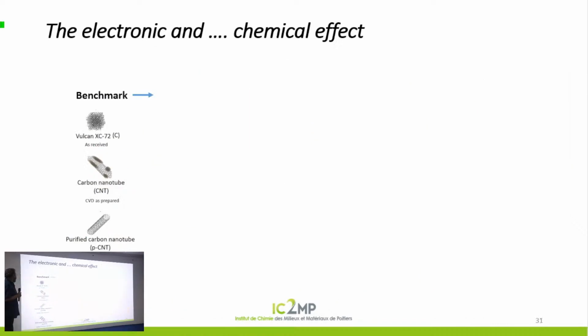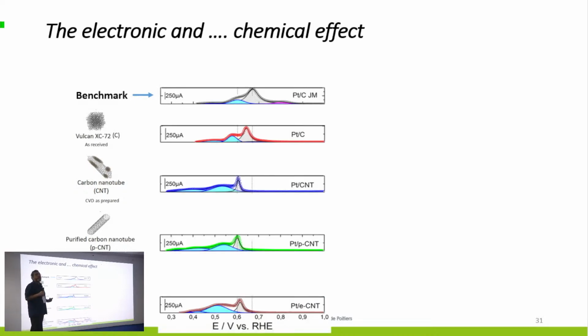Because now what we did is taking into account this support, we did the CO stripping. I don't know if you know what CO stripping is. You polarize the material, you adsorb CO, and this CO adsorbs in a monolayer. Then you scan the potential, and you will observe that the adsorbed CO will be oxidized to CO2. CO is a very interesting molecular probe because it really probes the electronic property of the material. That is a very interesting tool. It's not very expensive at all. And that's indeed what you observe here.